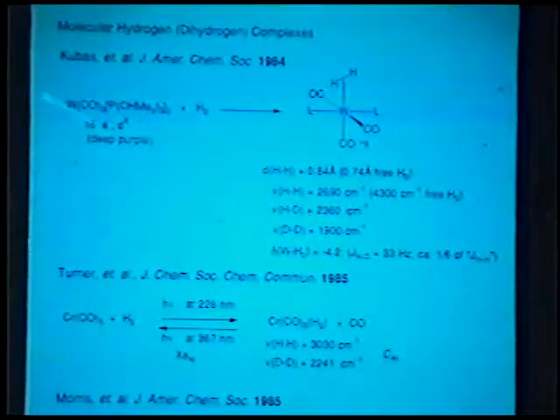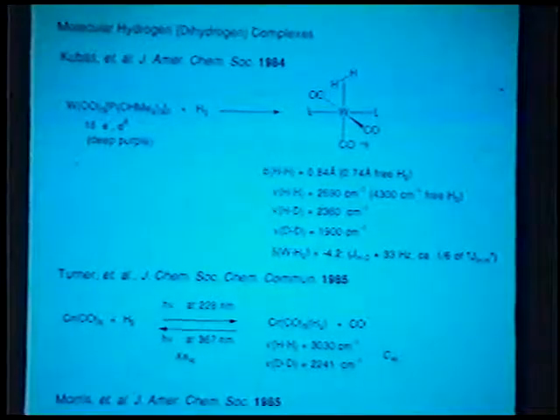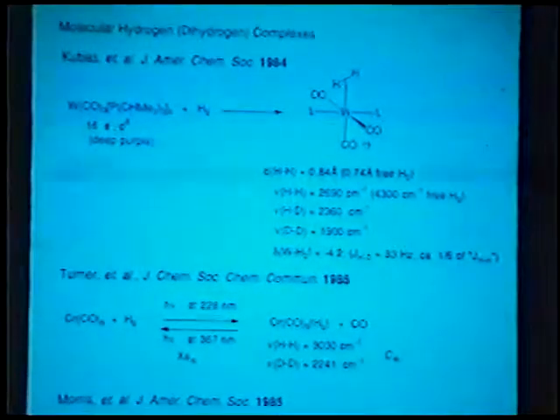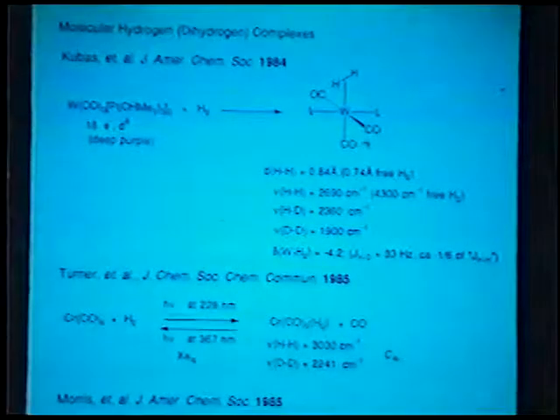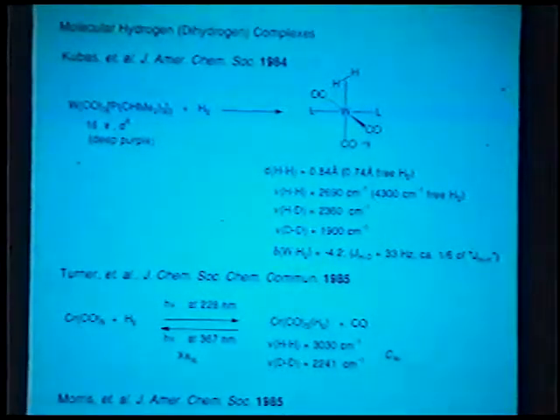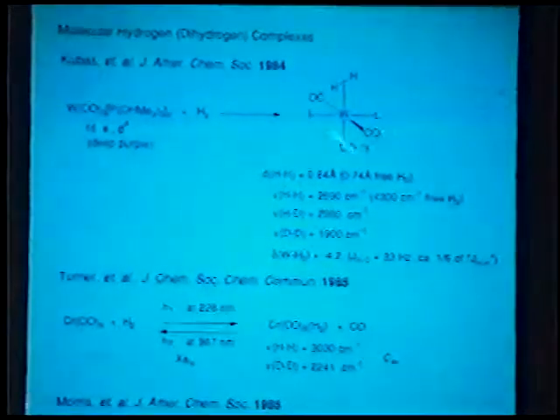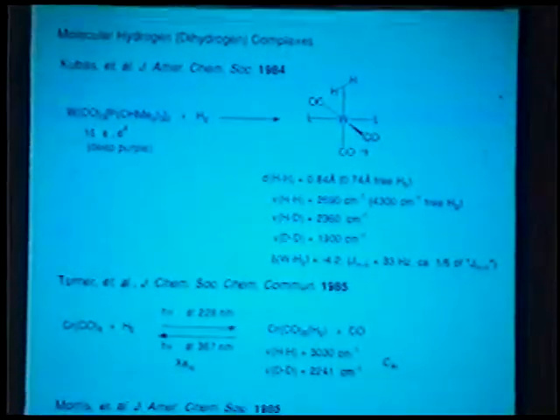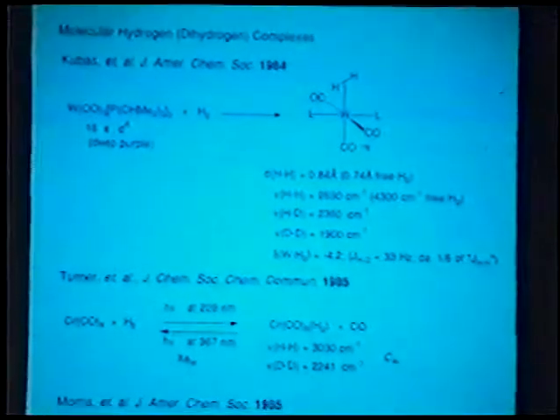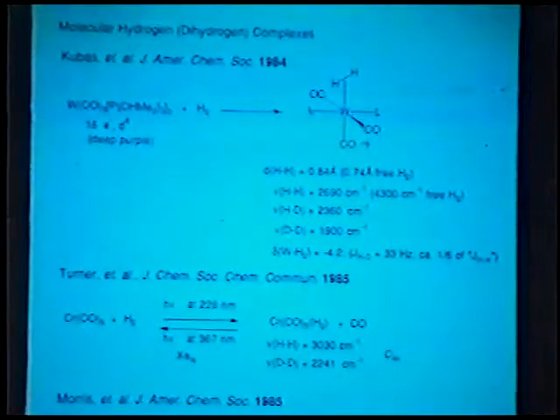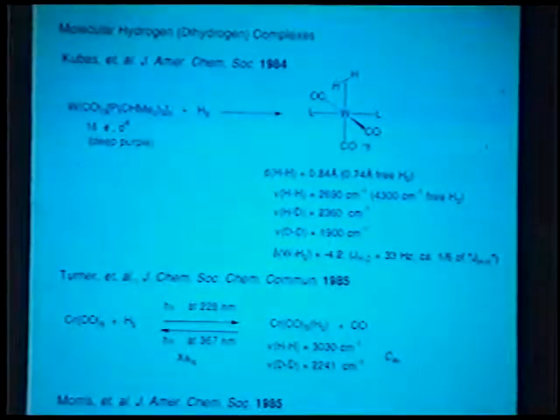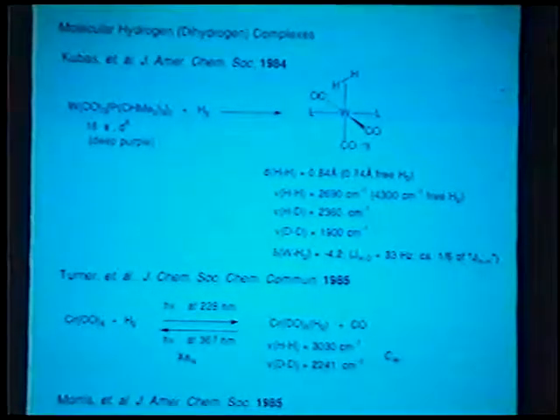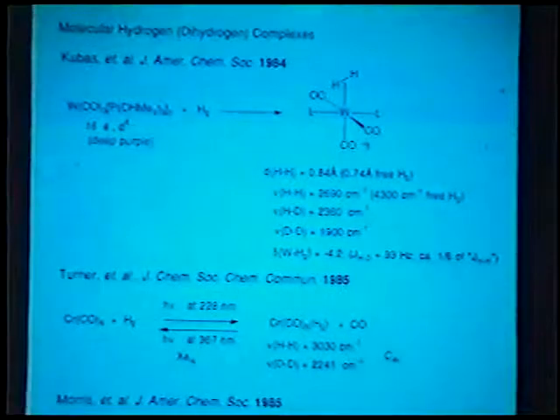They're commonly found with these d6 metal centers with either a cationic charge or electron acceptor type ligands that would retard the tendency for the metal to fully oxidatively add, that is, raise its oxidation state by 2. So these plus charges and electron deficient nature of the metal center in general tends to discourage the full oxidative addition. You can think of these as being sort of arrested oxidative addition. Crabtree has pointed out that the close proximity of the 2 hydrogen nuclei greatly shortens the T1s in the NMR for these metal hydrides. And he's used this criterion to estimate HH distances in a number of polyhydrides and shown that many of these are likely to be dihydrogen complexes rather than polyhydrides.